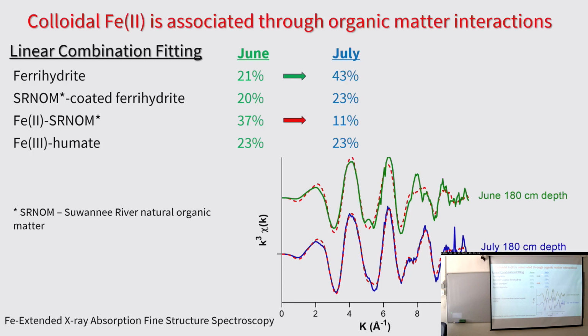However, in July, you can see those trends are reversed. We have an increase in the contribution of ferrihydrite and a drop in the contribution of iron 2 organic matter interactions. These go down to be merely 11%, showing that the July or summer colloids are more oxidized in nature. So these results here really exemplify the dynamic and delicate composition of these colloids.